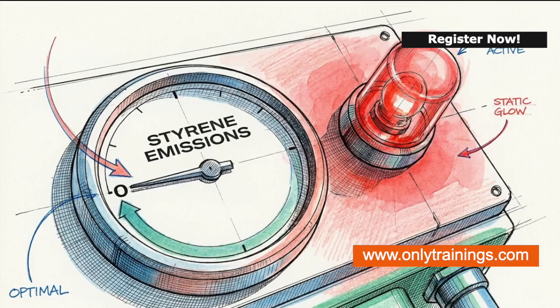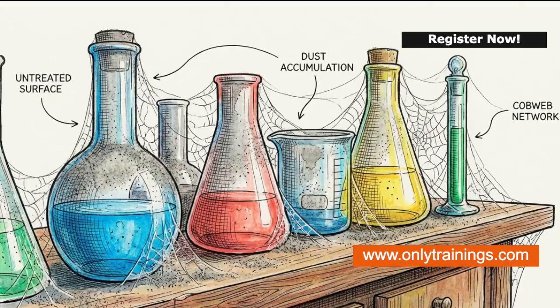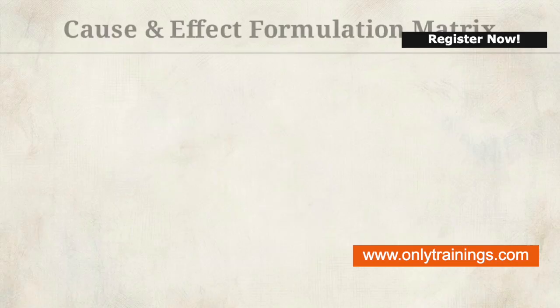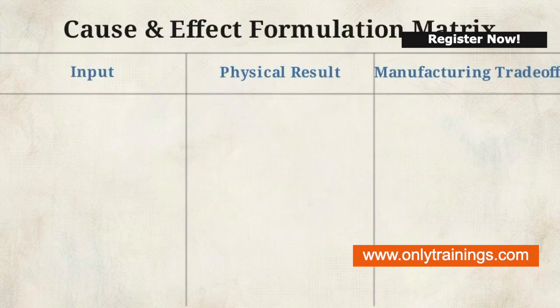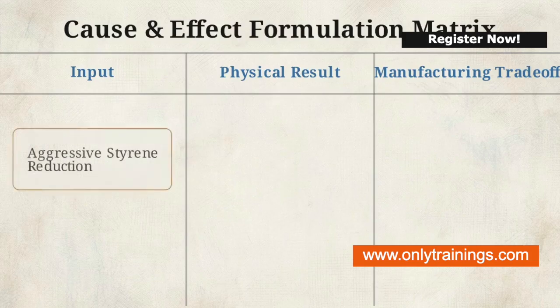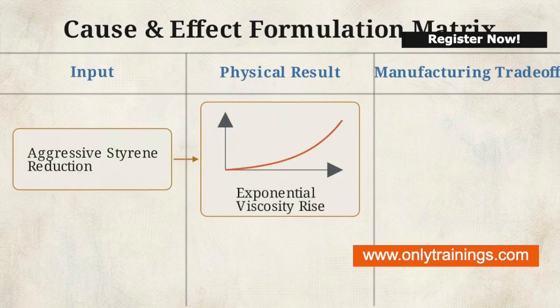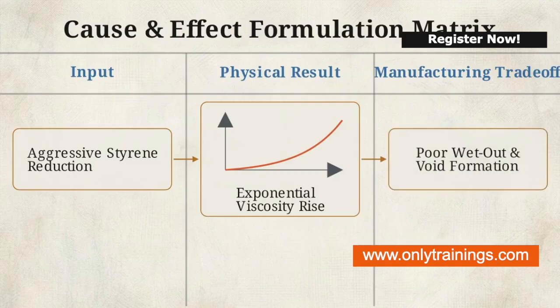Let's look at the first common formulation trade-off: cutting styrene content purely to satisfy immediate emissions targets without adjusting the rest of the chemistry. This cause and effect formulation matrix maps out the consequences. Aggressive styrene reduction results in an exponential, uncontrollable spike in base resin viscosity. Applied to dry reinforcement fibers, the manufacturing trade-off is a complete breakdown in wet-out.